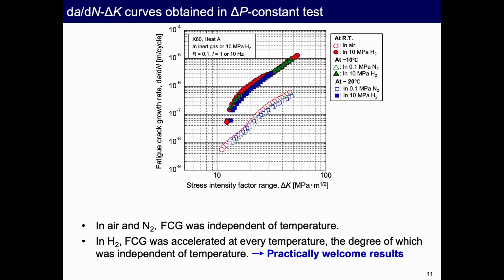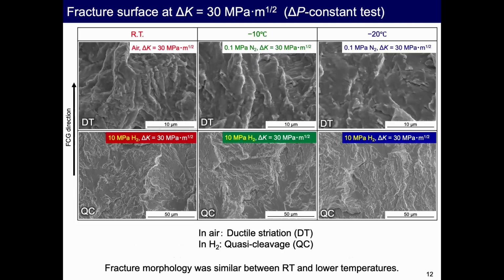And in hydrogen gas, the solid marks indicate the experimental data. The crack growth was accelerated at every temperature, the degree of which was independent of temperature. This is a practically very welcome result. If we observe the fracture surface, for example at delta K of 30, this is room temperature, -10, -20, with air or nitrogen and hydrogen on the lower side. Briefly, I can say that the fracture morphology was similar between room temperature and lower temperature.